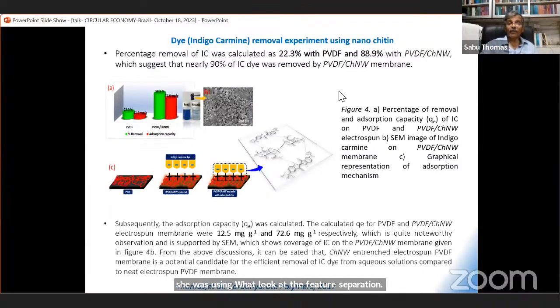Then I suggested, why can't we combine PVDF and nanochitin? Then we made a hybrid configuration by electrospinning. We introduced nanochitin with PVDF, and we went for the electrospinning process, and we made a membrane, and then we tried to purify the water. And we found that indigo carmine removal was increased to 88.9% when we used a configuration of PVDF and nanochitin. So see, a lot of possibilities of combining nanochitin with other polymers. Then you can increase the separation efficiency. This is something very interesting.